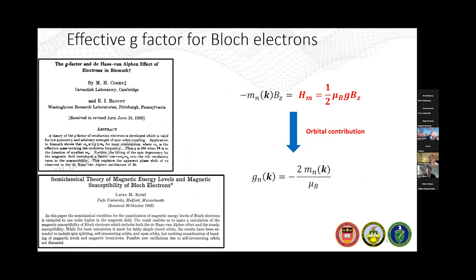So another way to think about this is in terms of the effective g factor. The g factor sets how much individual electronic states are going to shift in energy as you apply the magnetic field. And in most materials, the g factor is very small. It's on the order of a fraction of a milli-electron volt per Tesla. So in most cases, you will not see any substantial change in the band structure as you apply the magnetic field. But in topological materials, and in particular these kagome systems, it turns out that this g factor can be substantially enhanced due to non-trivial Berry curvature effects. And this is something that we're going to argue actually underlies many of our observations in these kagome materials.